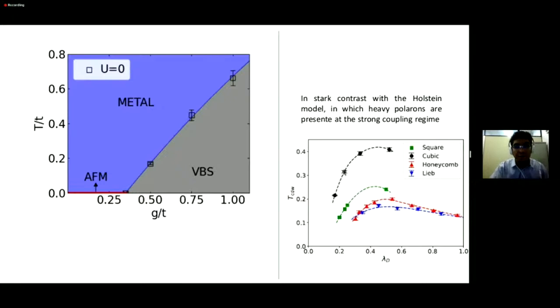Here, just for comparison, I present what happens in the Holstein model. In the Holstein model, despite the different lattices, the critical temperatures are not so high, and all of them present one maximum, which corresponds to the crossover from light polarons to heavy polarons. But in our case, for the SSH, we don't have this kind of maximum. And moreover, the critical temperatures are much higher than the Holstein ones. So it's one hint. It provides strong evidence that we really have light polarons in this case.